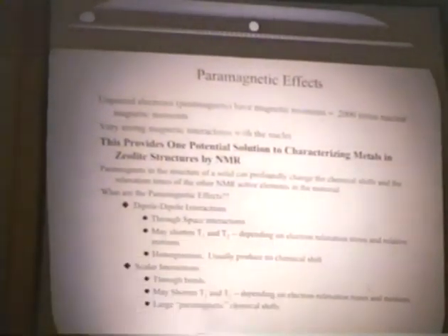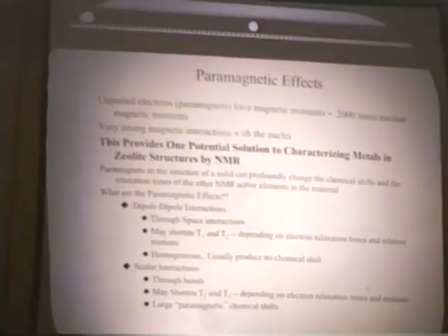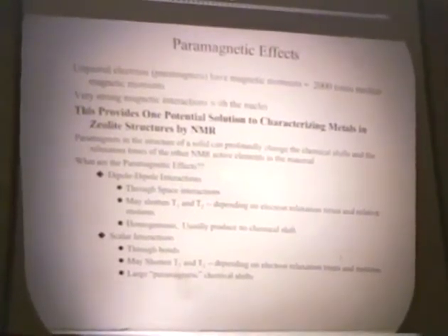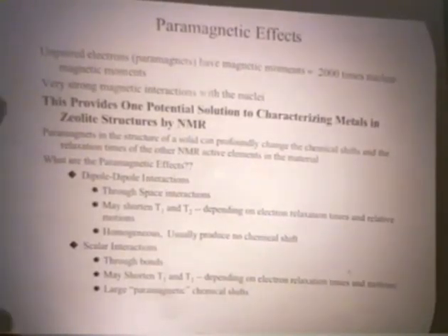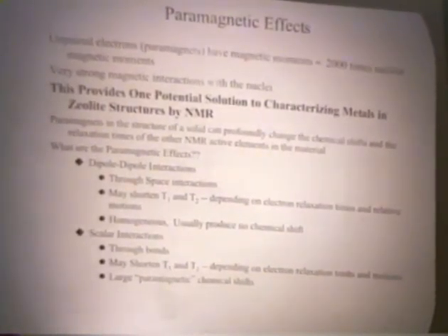Now, that's a nice cartoon, and it may make some sense. However, it would be nice to have some data as to where the titanium is really located in these materials. Of course, that's a tough problem. We're seeking out ways to examine where the titanium is. If the titanium is sitting on the surface, it's tetrahedral. If the titanium is sitting down in the wall of the silicate, it's also tetrahedral. And so the local geometry probably isn't going to change dramatically.